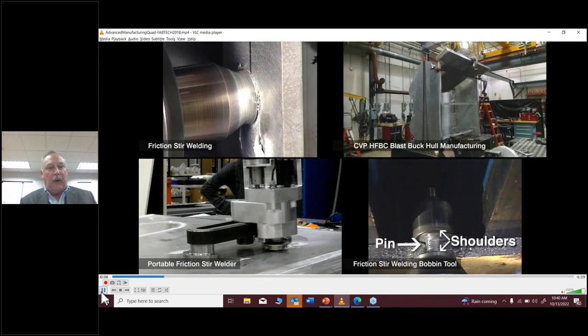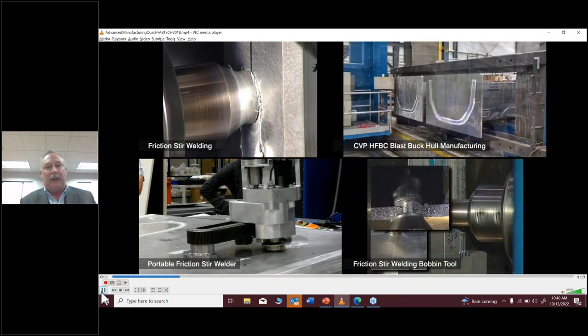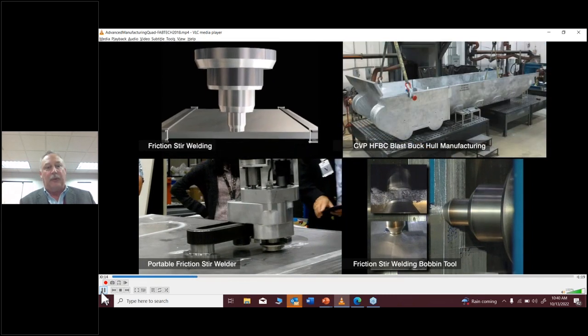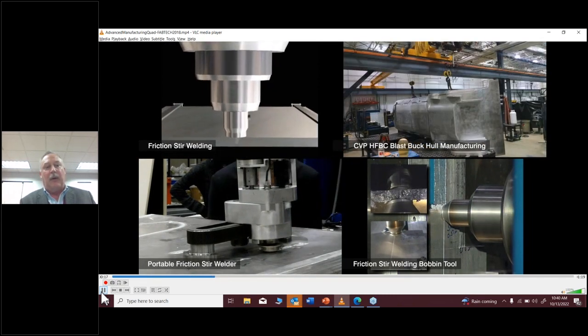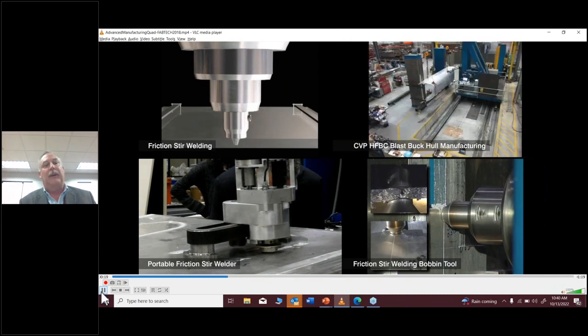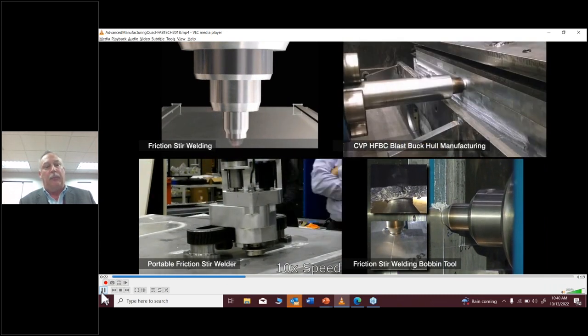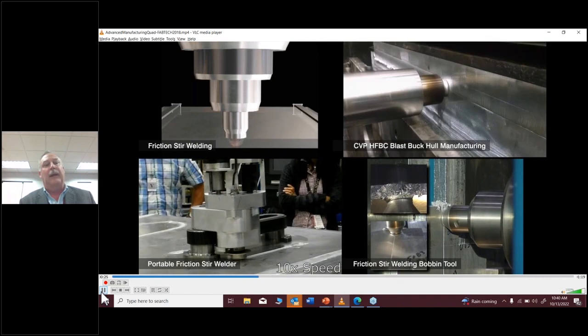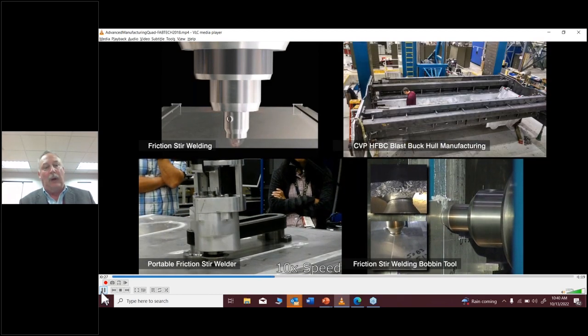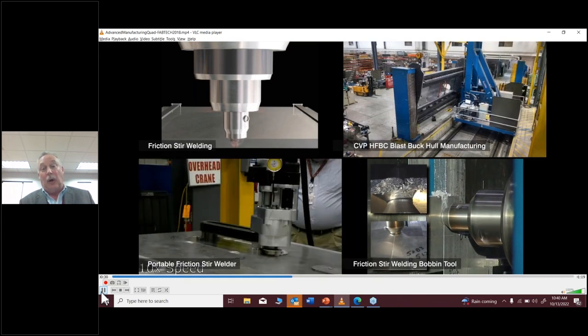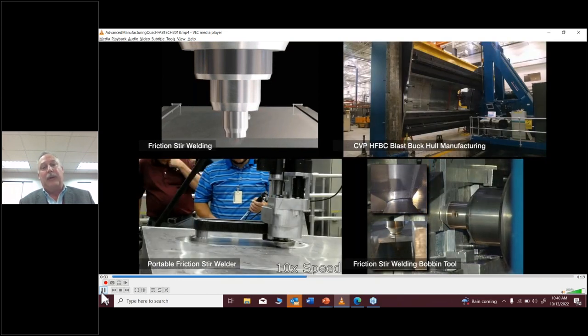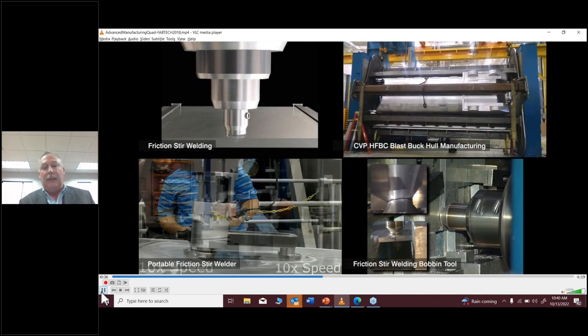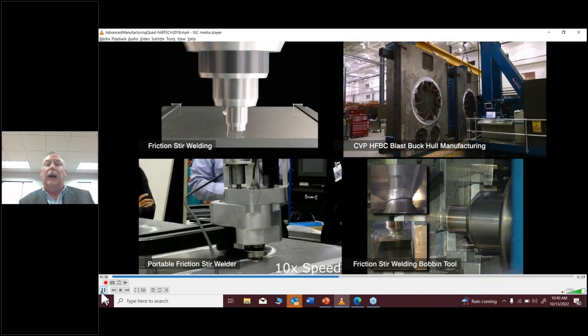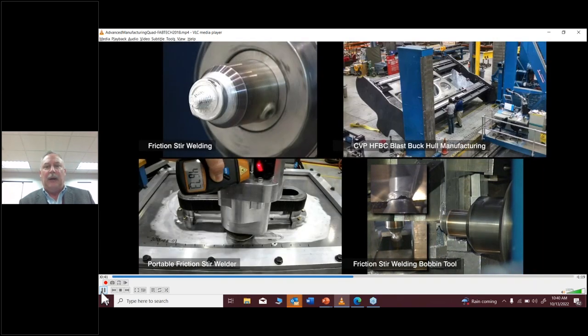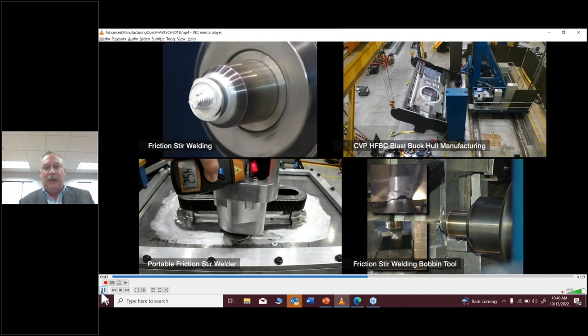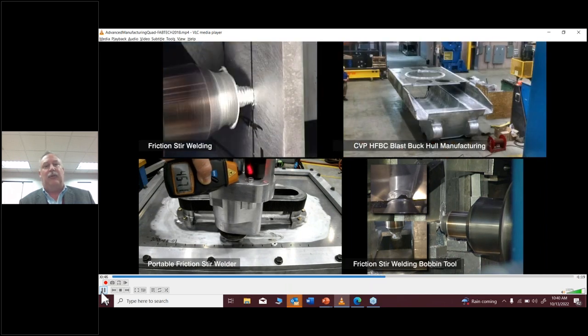So here's a quad video of some different tooling, different applications performing friction stir welding. It's very diverse. There's traditional tools that you see in the top left where you have a single probe penetrated into the material, rotating and doing a full penetration weld. And then in the lower right corner, that is a self-reacting tool or a bobbin tool that has a shoulder on each side of it. So both of them have their benefits in particular applications. Both make a very homogeneous weld in the material.